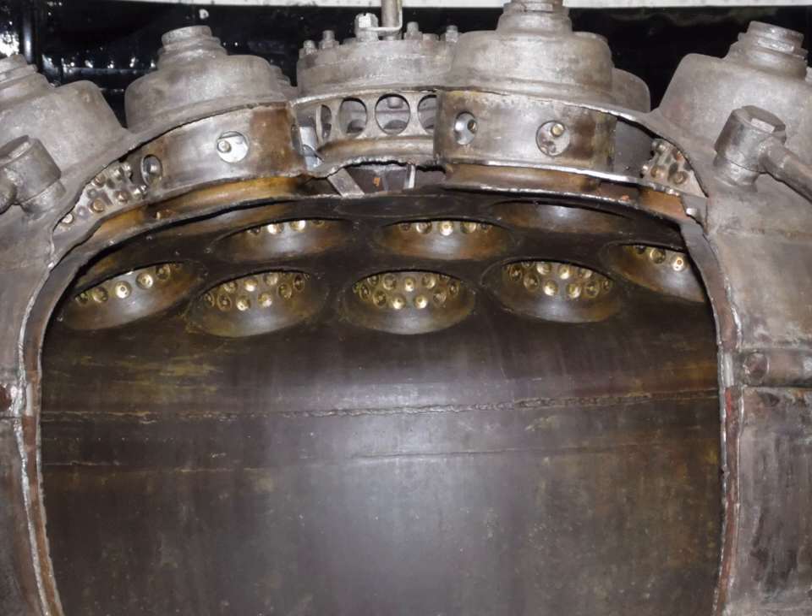The inner liner is usually constructed of relatively high temperature, high thermal conductivity materials — traditionally copper or nickel based alloys. Several different manufacturing techniques can be used to create the complex geometry necessary for regenerative cooling. These include a corrugated metal sheet brazed between the inner and outer liner, hundreds of pipes brazed into the correct shape, or an inner liner with milled cooling channels and an outer liner around that. The geometry can also be created through direct metal 3D printing, as seen on some newer designs such as the SpaceX SuperDraco rocket engine.